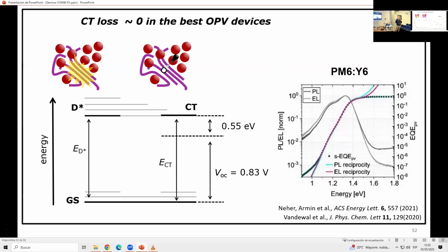So the best organic solar cells now are like this. If you draw this diagram, we can't see this extra absorption in the gap anymore. And if we use it as an LED, it's basically neat acceptor emission in this case. We don't see any subgap absorption anymore. So I guess we're in this situation: the CT state is the same or a bit higher, or at least it's still under debate what actually happens when they become very similar in energy because they couple and so on. But that's the case now in the best organic solar cells.